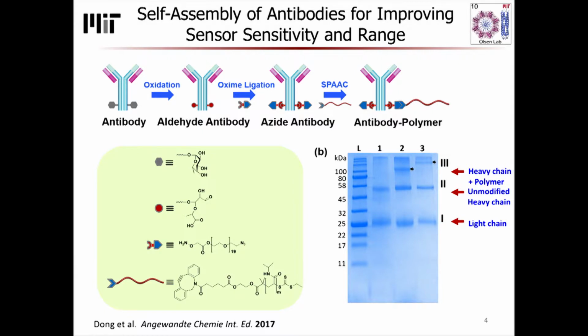So the approach we take to this is actually using engineered proteins into fusion constructs and block copolymers to fabricate nanomaterials from globular proteins. So I show here briefly a synthetic strategy for taking an antibody and selectively functionalizing it at its base with just a single polymer in order to form what looks like a block copolymer, where one block is a synthetic polymer, in this case N-isopropyl acrylamide, and the second block is an entire folded human IgG antibody. And due to steric occlusion of the second reaction site, once you get one polymer reaction, we basically can form just one-to-one block copolymers, which is what I show on the protein gel here.